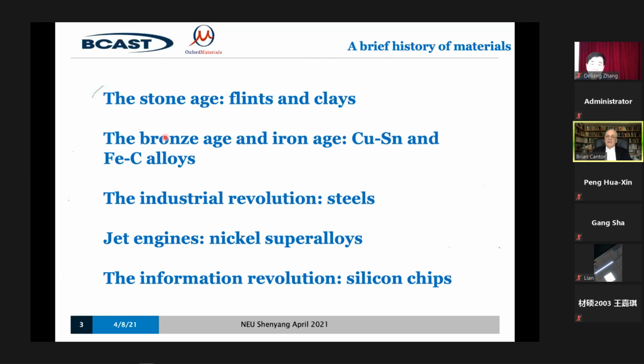It's a hard material, because the copper, the soft, moldable, formable, castable copper can now be made hard because of the copper-tin intermetallic compound, which precipitates, Cu3Sn, and gives the hardness. So that was the Bronze Age.